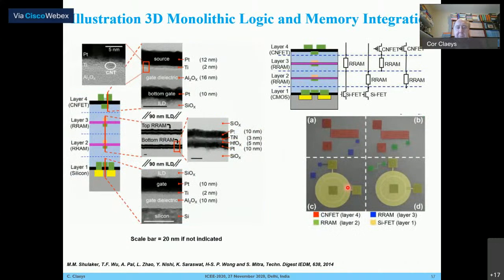Here you see an example from Stanford, where they have put 4 different layers on top of each other: one silicon layer, one layer for resistive memory devices, a second layer for resistive memory devices, and one layer for carbon nanotubes. They did the first process, the silicon devices, using the standard high temperature processing, and then they used lower temperatures, lower than 200 degrees centigrade, to do the fabrication of the different types of devices.